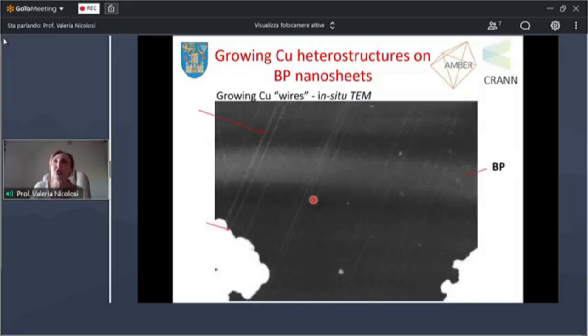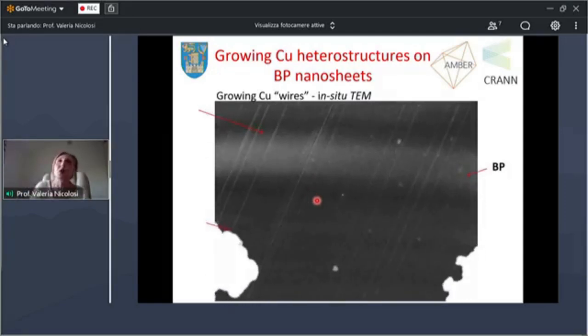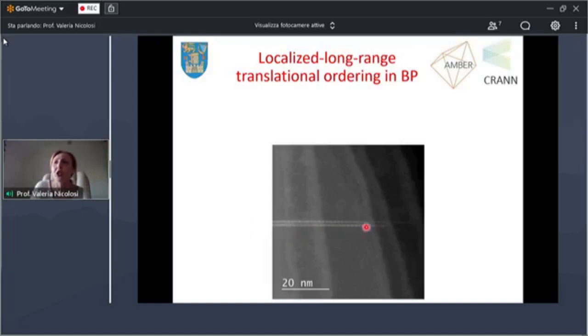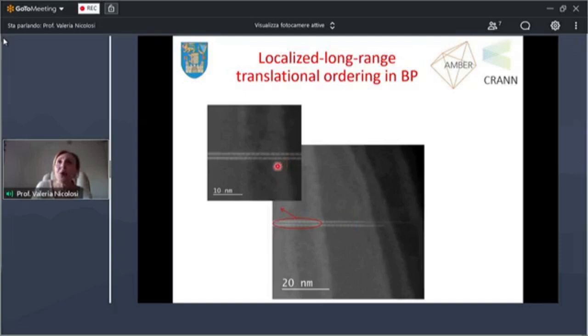This is an in situ TEM video where you show the formation. This is on black phosphorus nanosheets, and you can see that we have managed to find a way to build and grow in situ wires on the black phosphorus sheets. These wires here are beautifully structured. You see here a wire coming across the layers of a BP nanosheet, and you can actually see how beautifully structured and very repetitive and very ordered these wires are.